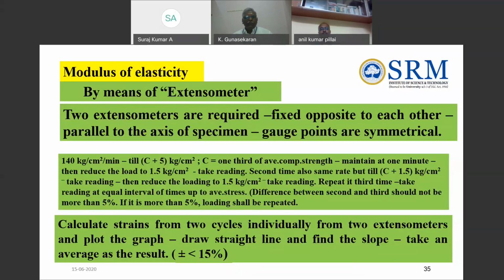Sometimes if it is not meeting this requirement, if it is not less than 5%, either the loading should be repeated or you have to recenter the specimen once again. Maybe centering is also a problem and that is why it is giving different values. So see that the centering of your specimen in your UTM is also perfect. Otherwise, you have to recenter it and repeat the same thing.